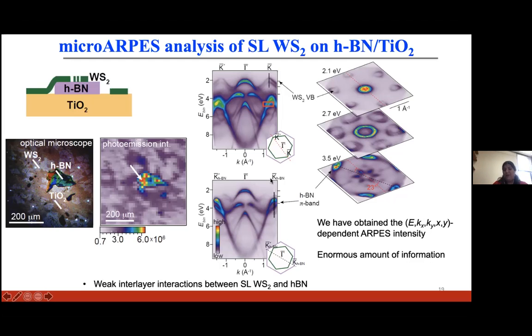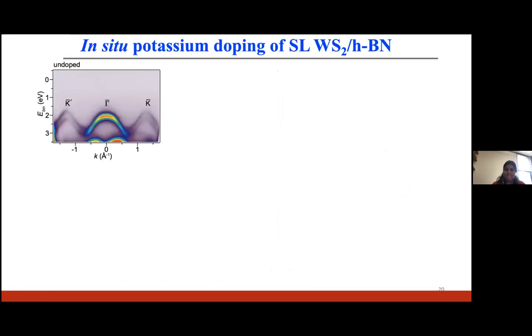By taking these constant energy cuts, which I'm showing here on the right, we can also extract the twist angle between our samples. What we found was that we have very weak interlayer interaction between our single layer WS2 and hBN. Now, let me show you what happens when we put potassium atoms on our sample. When I say we are putting potassium atoms, we are essentially putting a lot of electrons in our sample.